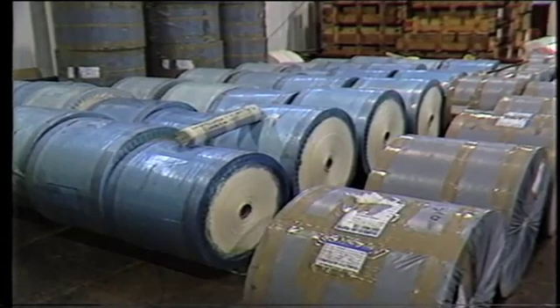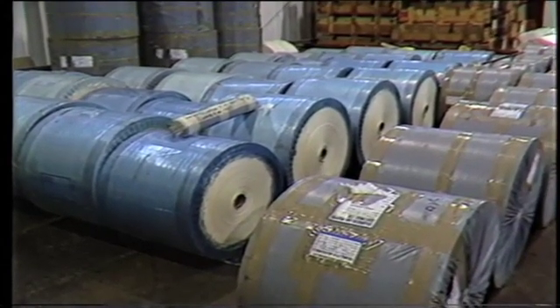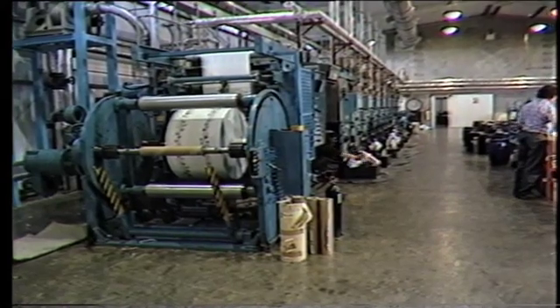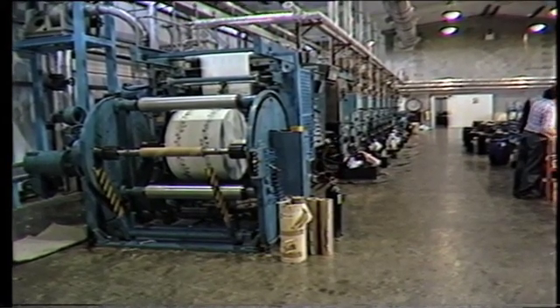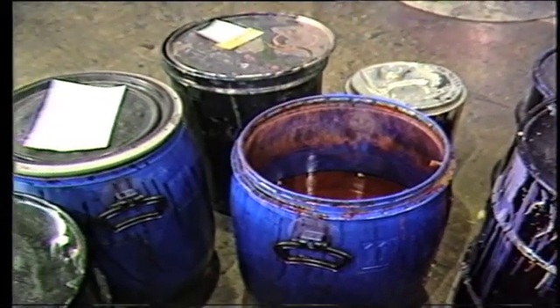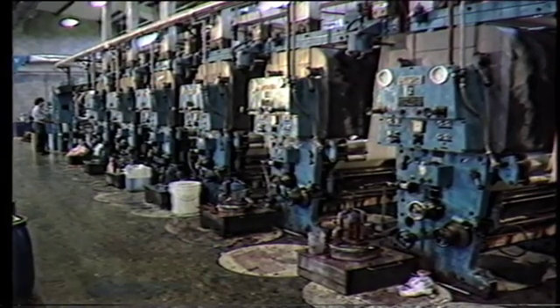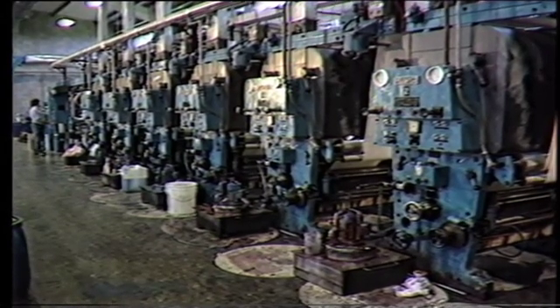Base paper with a high plastic content is used to produce vinyl wallpaper, but gravure printing is quite different to rotary screen printing. Solvent inks are used in place of print pastes, as these key better to the vinyl base paper. They also dry quickly, so faster machine speeds can be achieved. Up to 7 colours can be applied.